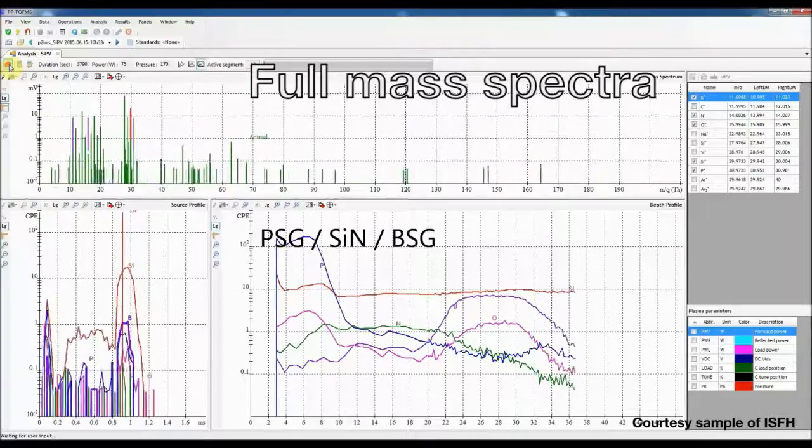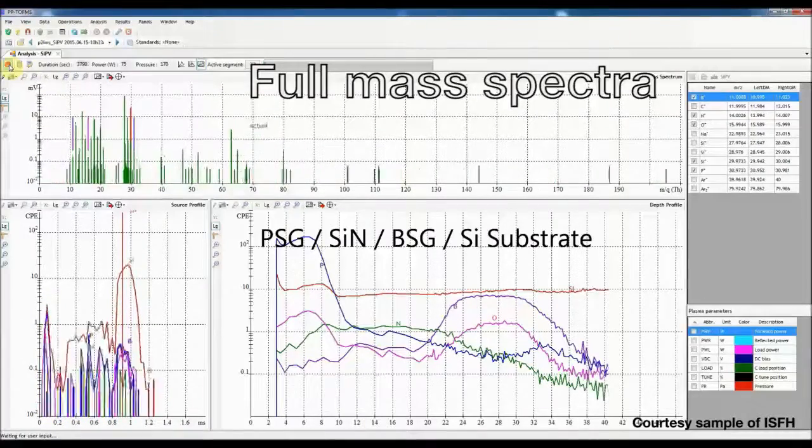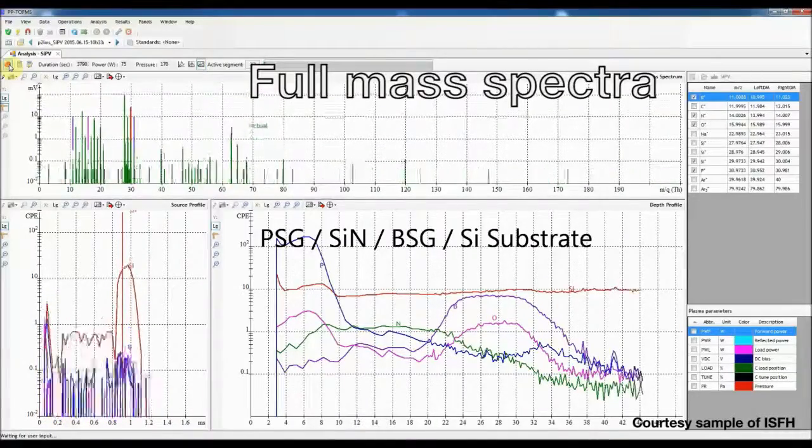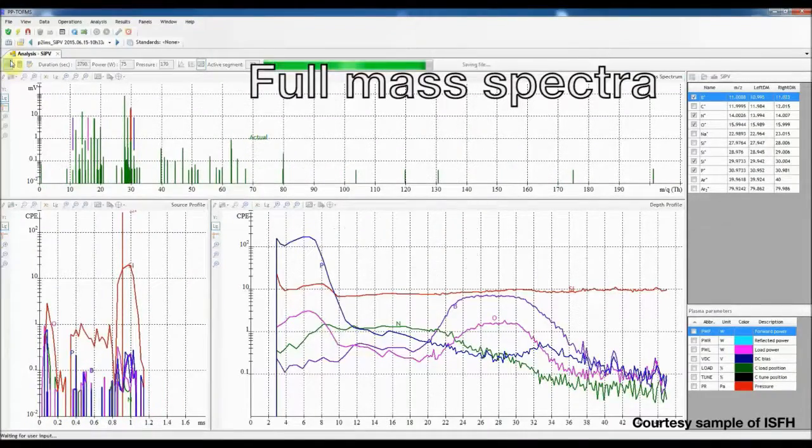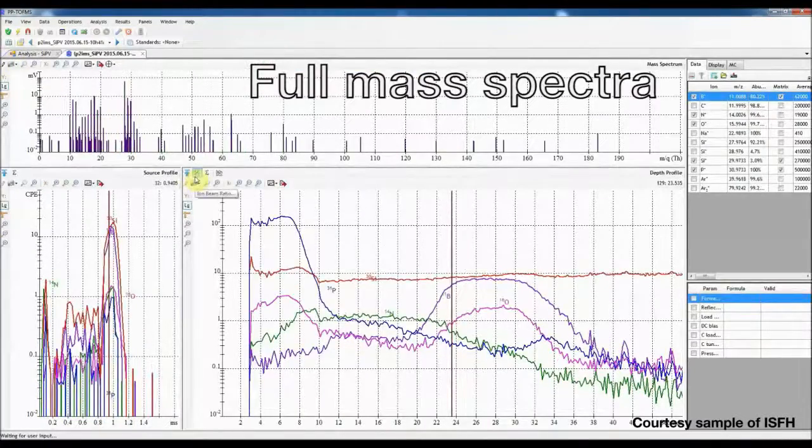The depth profile for this 800nm stack is obtained in 30 seconds, and the analysis including sample positioning and flush is done in less than 5 minutes.